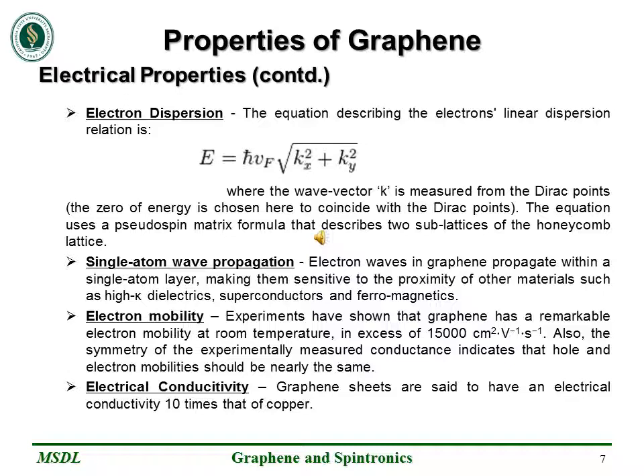Experiments have shown that graphene has a remarkable electron mobility at room temperature in excess of 15,000 centimeters square per volt second. Also, the symmetry of the experimentally measured conductance indicates that the hole and electron mobilities are nearly the same in graphene. Graphene sheets are said to have an electrical conductivity 10 times that of copper.